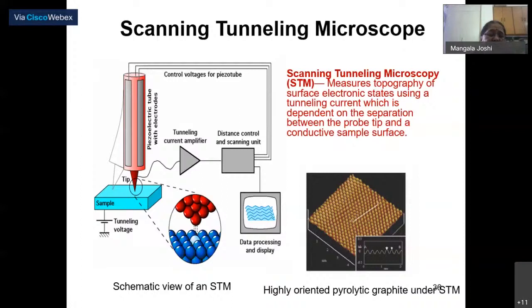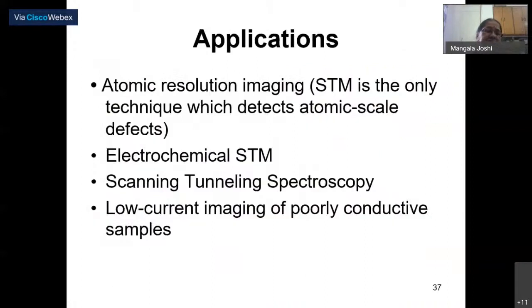On the right, you can see a highly oriented graphite sheet under STM. You can see very clearly how the graphitic sheets have been arranged in a very oriented fashion. STM measures the topography of the surface electron states using a tunneling current, which is dependent on the separation between the probe tip and the conductive sample surface. So this is the basics of scanning tunneling microscopy. Applications of STM are atomic resolution imaging, which I think mostly physics people do. Atomic scale defects can also be found out. Poorly conductive samples can also be done here, unlike SEM and TEM.